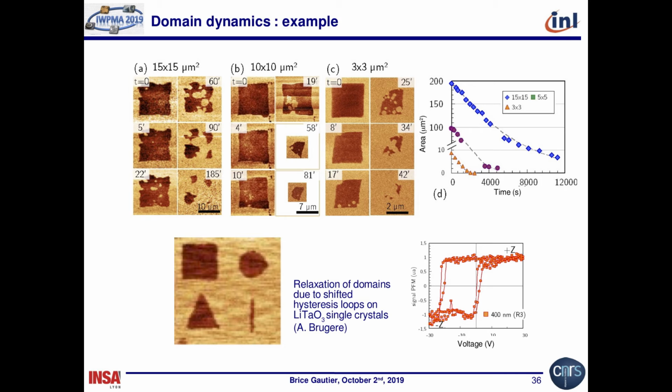The problem is that it has been transferred on a host substrate by smart cut. And after this, you have a strong shift of the hysteresis loop with respect to the voltage axis, like this. And if you try to create by yourself with the AFM tip this region of opposite polarization there, what you see, if you wait 5 minutes, is that some regions are flipping back. 22 minutes, okay, you have nucleations of domains which are flipped back. 60 minutes, 90 minutes, and so on. If you wait for a sufficiently long time, then the domains disappear